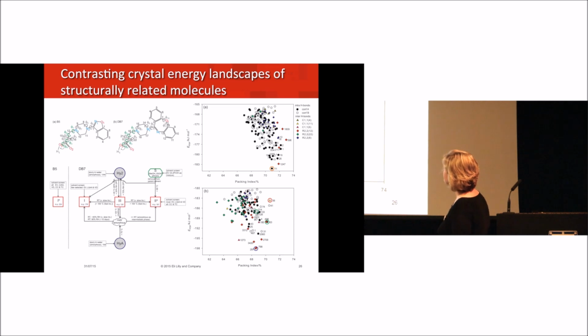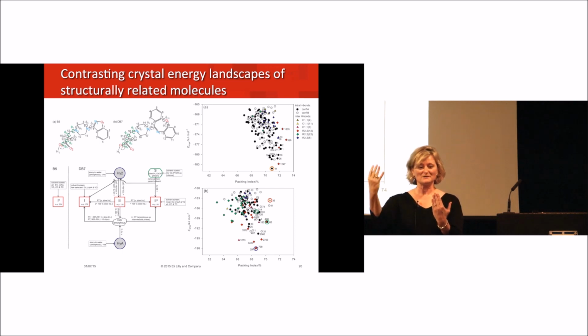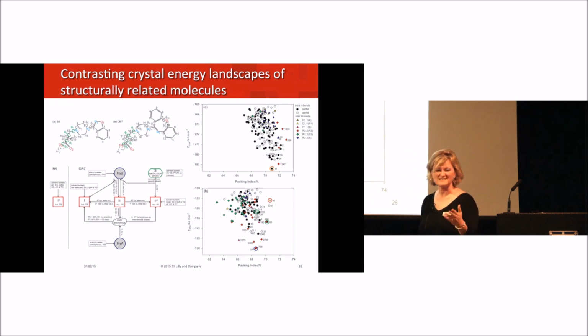What you can see from the two crystal energy landscapes is one of the molecules in general has a much better propensity to pack in dense structures than the other. And if you look really closely, you'll find out that despite the conserved hydrogen bonding, one of the molecules tends to form low energy structures with intramolecular hydrogen bonds and the other with intermolecular hydrogen bonds. And these sorts of things wouldn't be predicted.